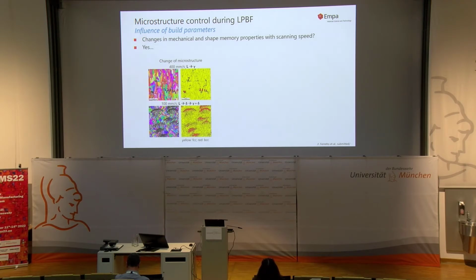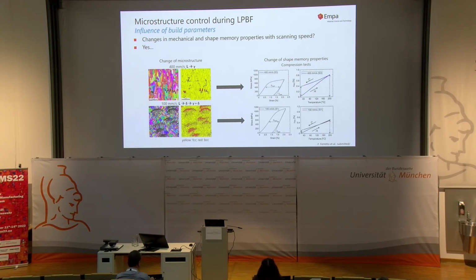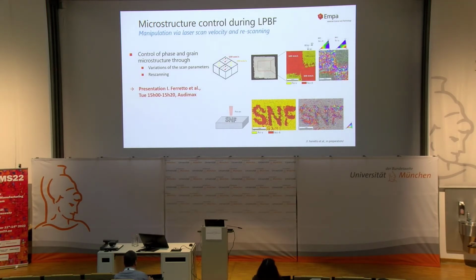Next question is, does this affect the thermomechanical properties? Shape memory effect? Yes, it does. So we checked that. Here are compression tests. Here you see also this nonlinear behavior, which is known for the shape memory alloys. In this case, we have a very pronounced shape memory effect. So if we have that microstructure, we have much higher strength, but reduced shape memory effect. And then we started playing around, and this is just meant as a teaser.